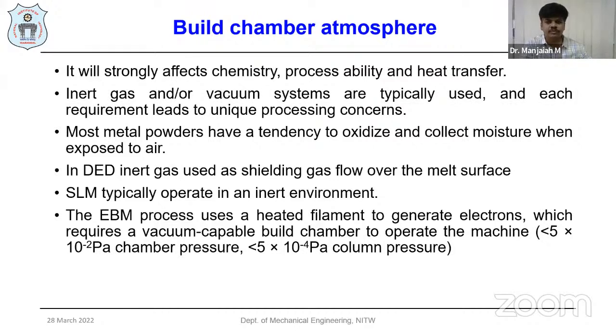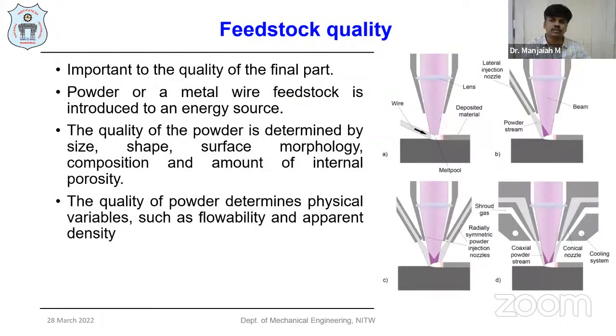Even in the EBM process, we use a vacuum chamber, with a heated filament used to generate the electrons. This requires a vacuum-capable chamber to operate the electron beam melting machines, which maintain a chamber pressure of less than 5×10⁻² pascals, and a column pressure of around 5×10⁻⁴ pascals, in this kind of electron beam manufacturing process.